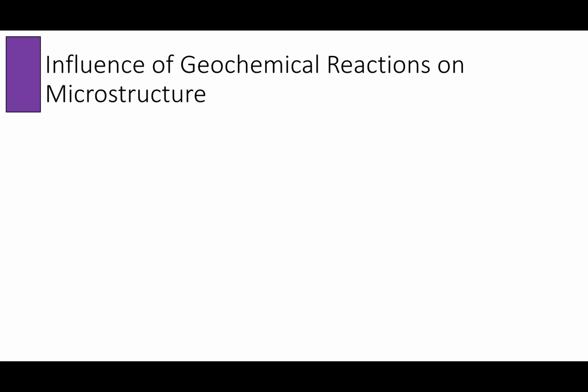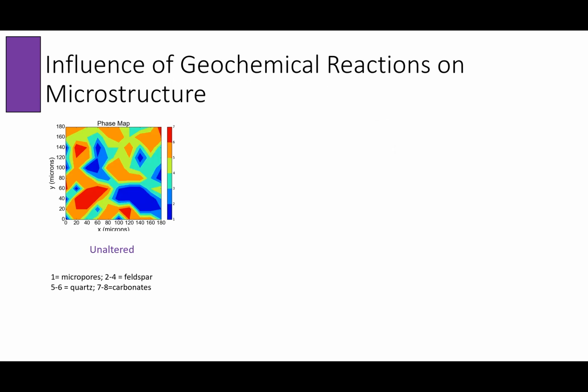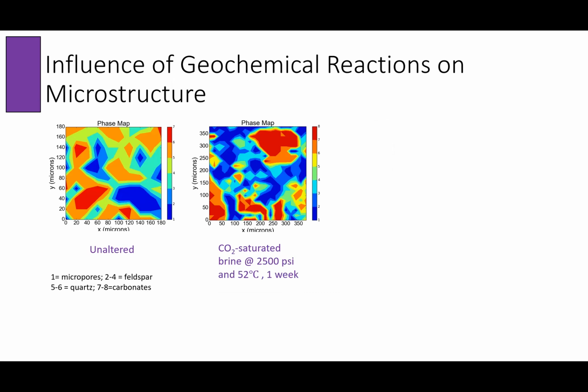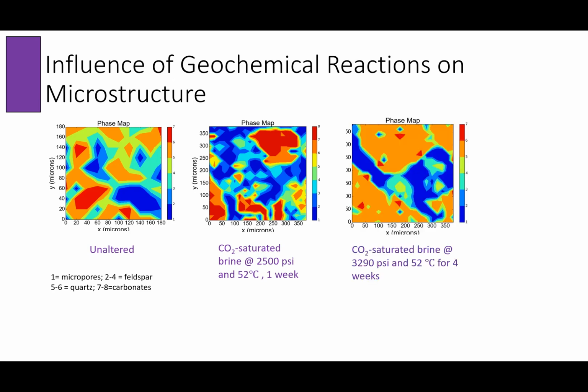So then the next question that we're asking is, what is happening and how does that microstructure and composition evolve as a result of incubation within CO2 saturated brine? So we looked at 3 conditions. We have the unaltered sample, we have the sample that's going to be incubated in CO2 saturated brine at 2500 psi and 52 degrees Celsius for 1 week, and then the sample that's going to be incubated in CO2 saturated brine at 3290 psi, so higher pressure, and for 4 weeks.